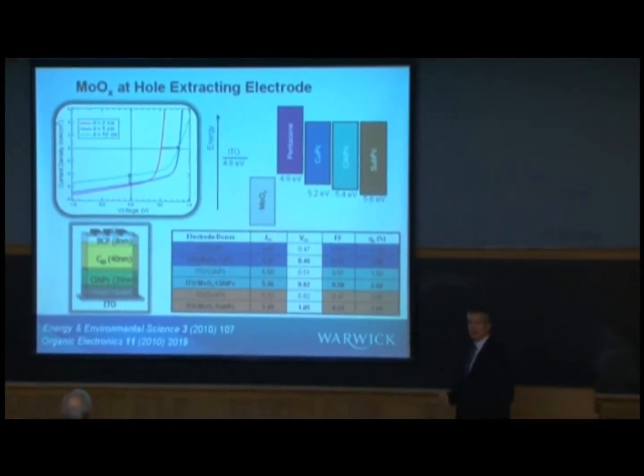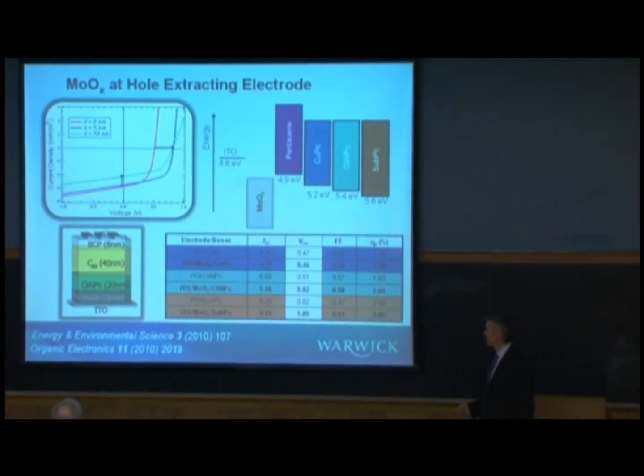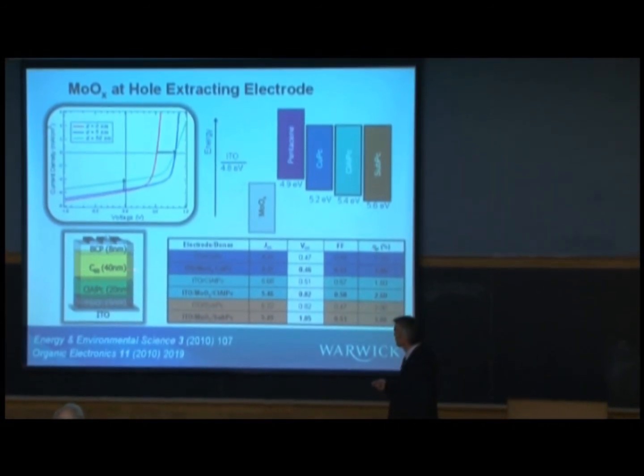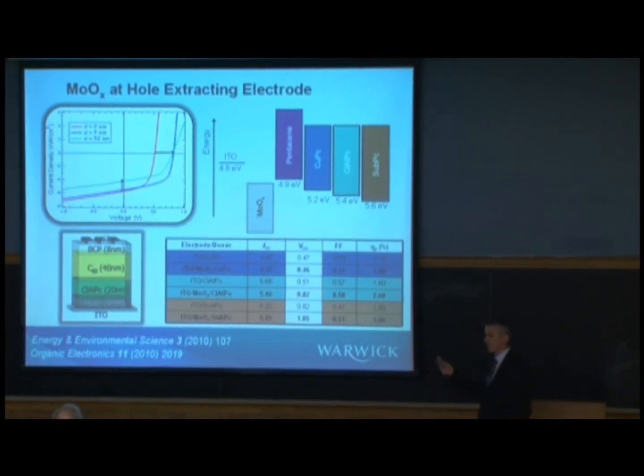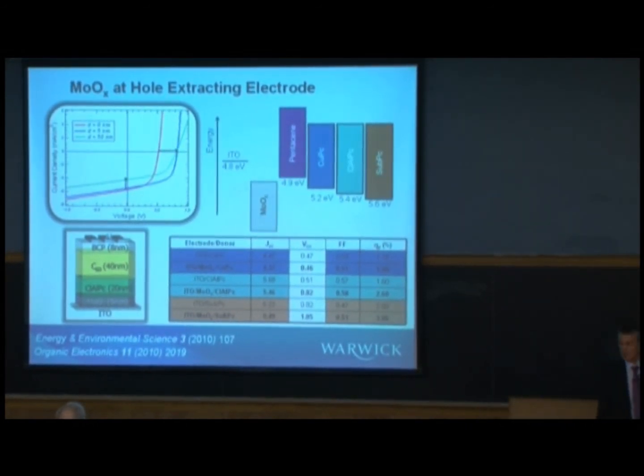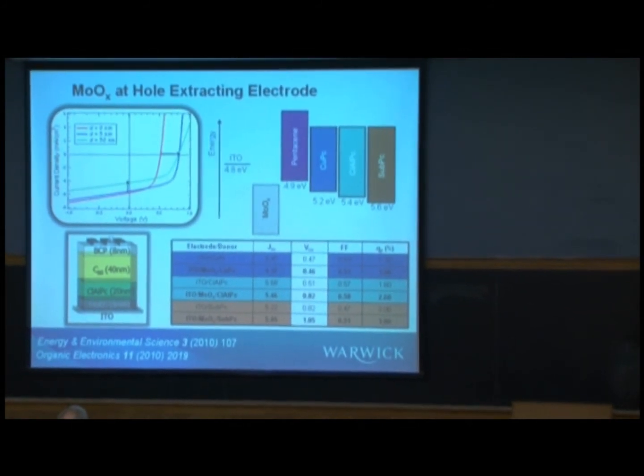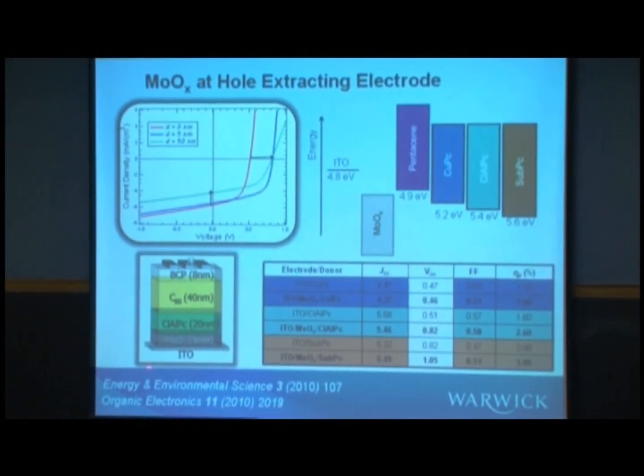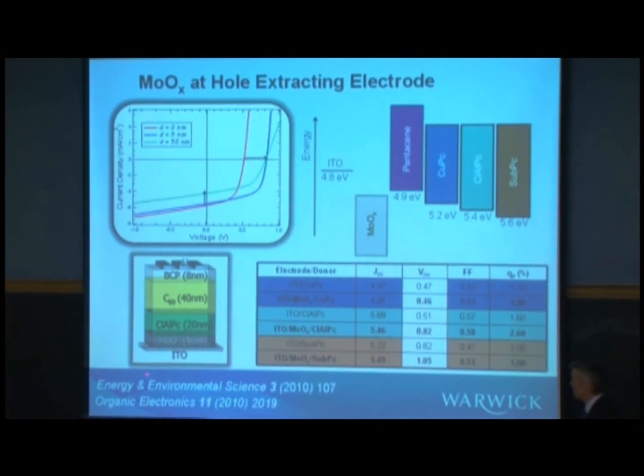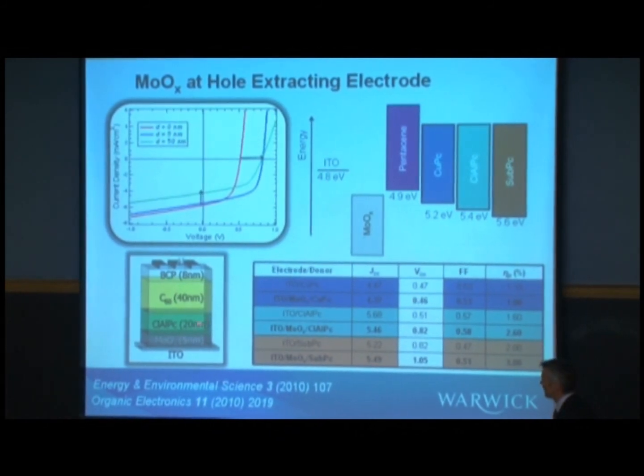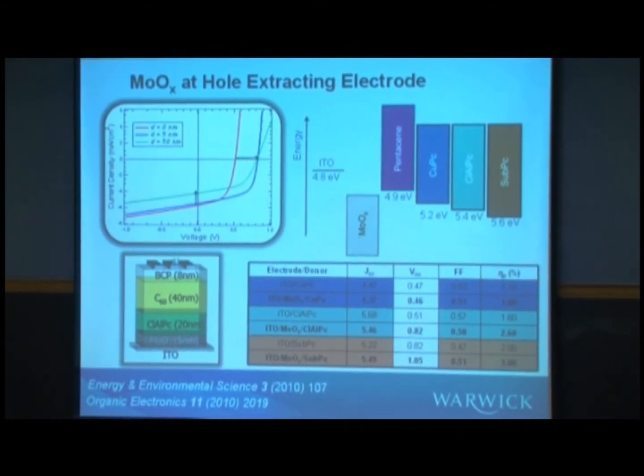So here's our basic device again, single junction device, phthalocyanine donor, C60 acceptor. So we'll go back to the simple devices at the beginning. And now what we're going to do is just insert a very thin layer of a metal oxide, molybdenum oxide in this case, at the interface between the indium tin oxide and the donor, the chloroaluminium phthalocyanine.